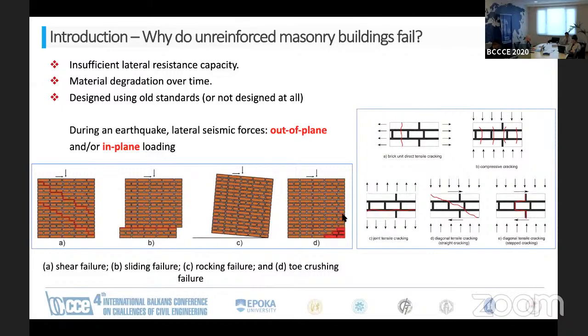Especially also inside the brick, it can crack during a vertical crack if the brick and the mortar do not have sufficient strength. It can crack during compressive cracking in figure B, or it can occur during joint tensile cracking along the mortar joint or diagonal, which is also a very dangerous failure, as well as diagonal tensile cracking in a step-like diagonal in the vertical plane of the wall.